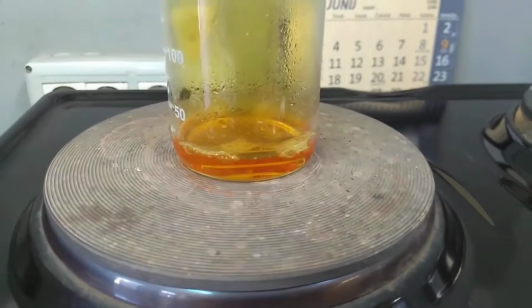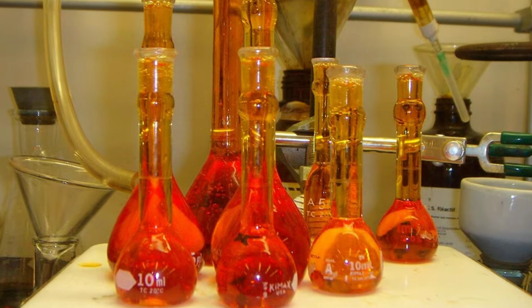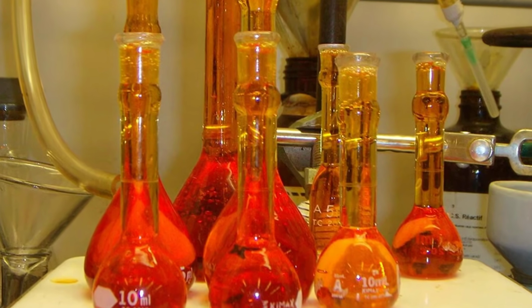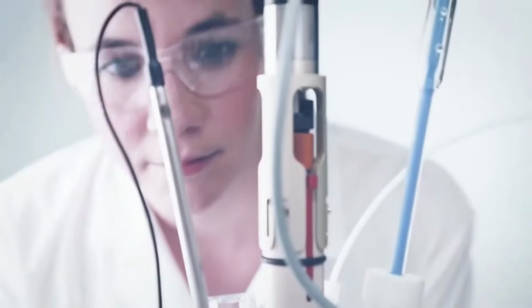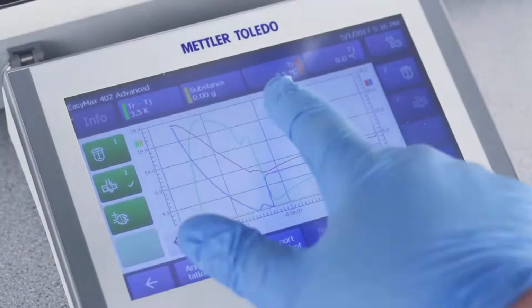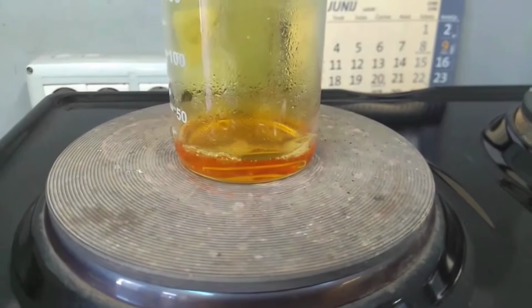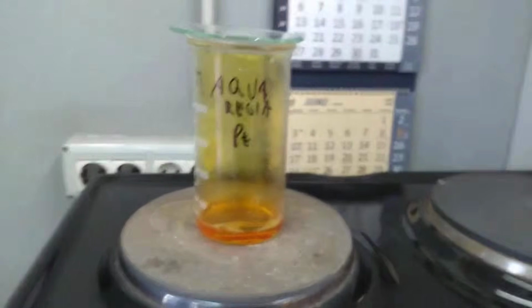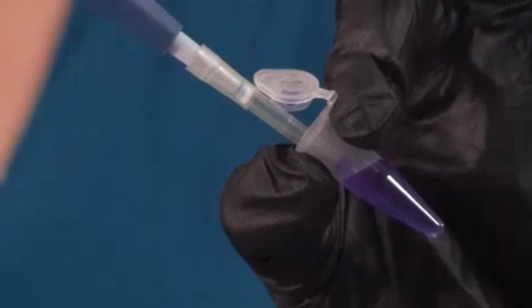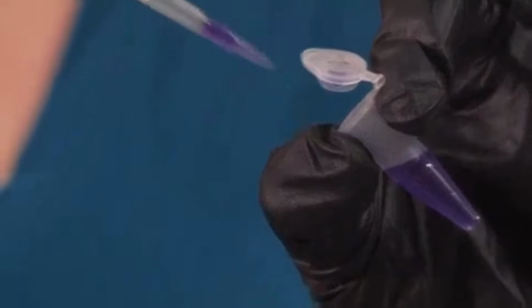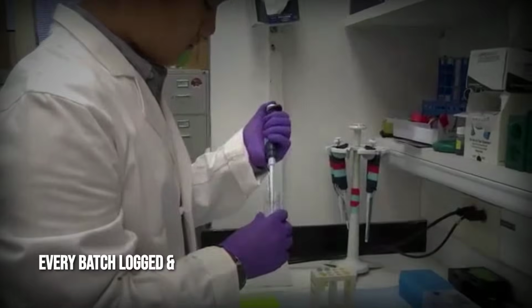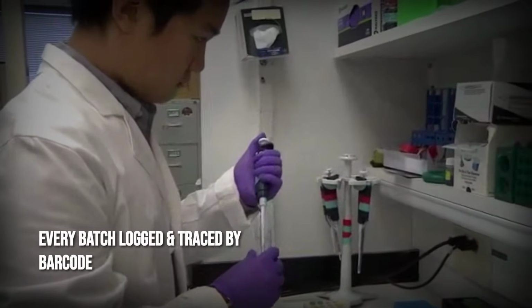Now comes the most delicate phase: dissolution in aqua regia, a potent blend of hydrochloric and nitric acids. This mixture, heated to just the right temperature, breaks down the platinum into a solution, leaving behind less soluble metals for separate recovery. Every step is measured in milliliters and minutes. Fumes are drawn away by powerful scrubbers, and each batch is tracked by barcode and logbook.